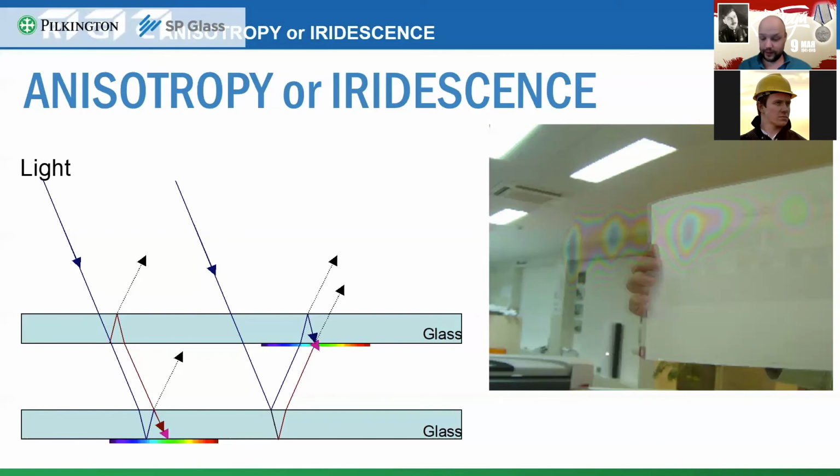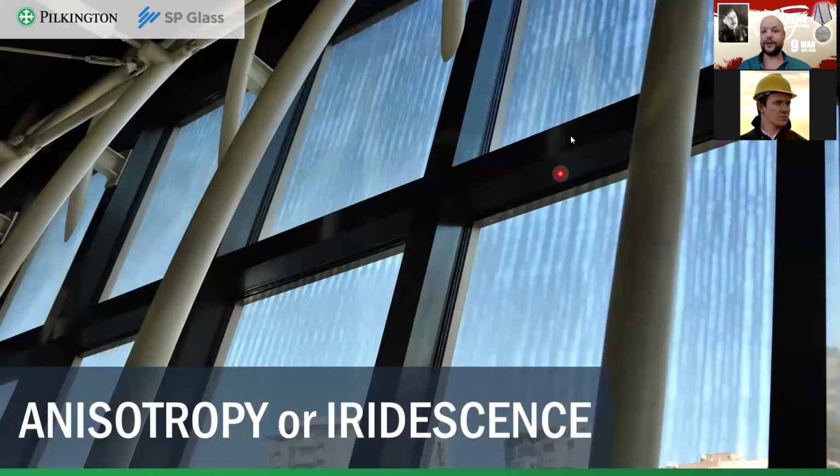And when you put your polarized sunglasses on and look at any tempered glass, you will most certainly see this. On a facade, you will see stripes. If you look at the tempered glass in your car, the back window or side window, you will see colored dots. And that makes polarized sunglasses the best way to tell whether the glass was tempered or not. Easy, cheap, and very, very simple.